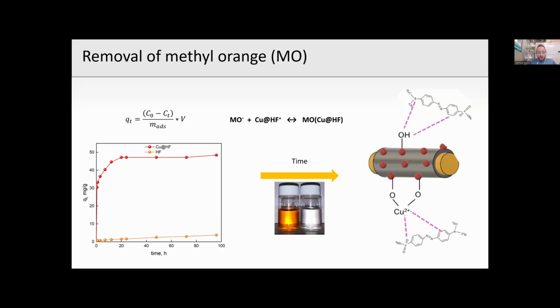A preliminary adsorption test was carried out just to compare the adsorption of copper-modified hemp fibers with the pristine hemp fibers. You can see the adsorption capacity profile on the left side, and it is possible to observe a great and noticeable increase in the adsorption capacity towards the removal of methyl orange from water effluents, which can be ascribed to different factors, such as the increase in specific surface area and the increase in positive adsorption sites due to the presence of copper oxide.